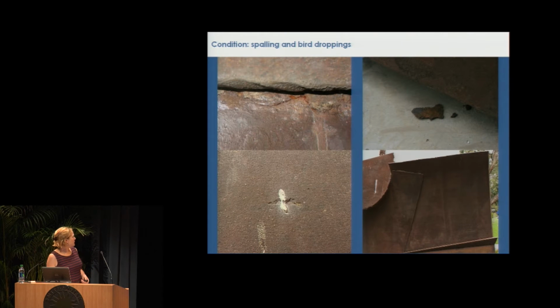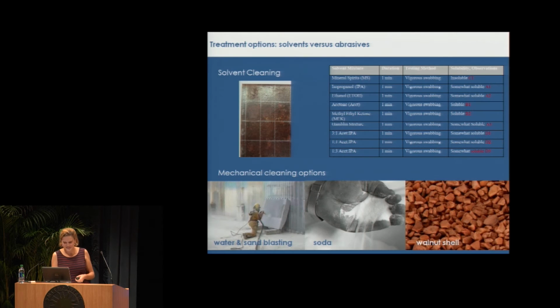So here you see also there was water damage and the corrosion. The water went underneath some of the coating, under the thick coating, and the corrosion made the metal fall off. So you had really quite large pieces. It's kind of a shame that I didn't put a measuring tape there. Quite large pieces of sculpture detaching. And then you had the regular stuff like bird droppings and footsteps of people walking on the sculpture. So I think it's kind of clear that the sculpture was not in good condition.